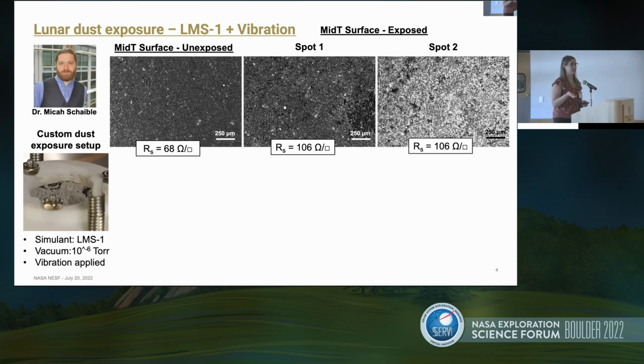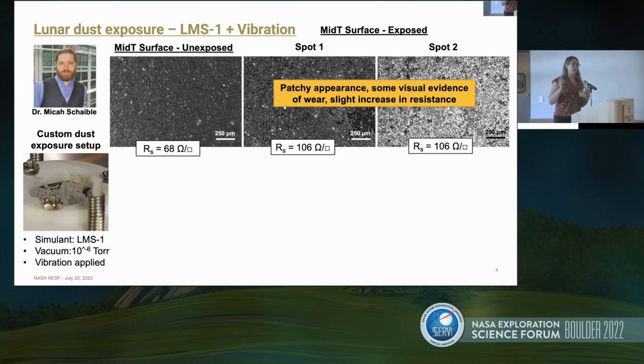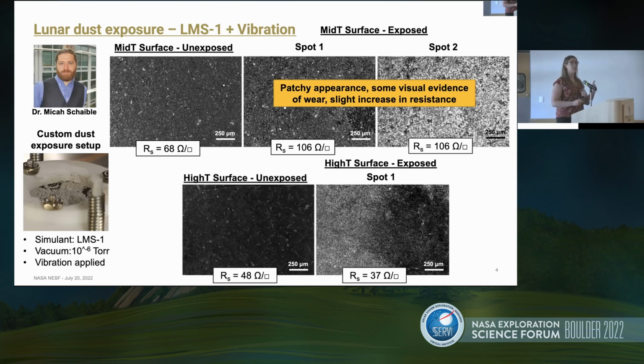When we expose these things to the lunar simulant condition, we do see that the surface resistivity goes up a little bit. That's sort of as expected as we get simulants stuck and sort of working its way down into these porous surfaces. And we maybe see a little bit of abrasion, which you can kind of make out in the lower right-hand corner of the middle image, where we've got a bit of texture variation in the optical image. So those surfaces are probably not the right choice, but if we progress to that higher processing temperature, so you remember that this is a fully infiltrated composite structure now, you can see in the optical image on the left that is a very smooth surface that looks to be relatively defect-free.